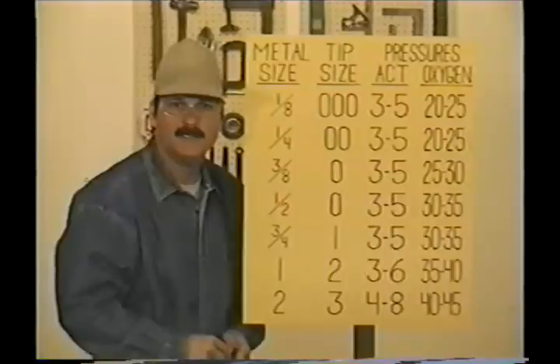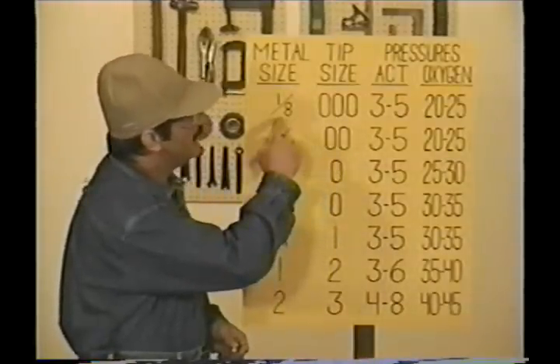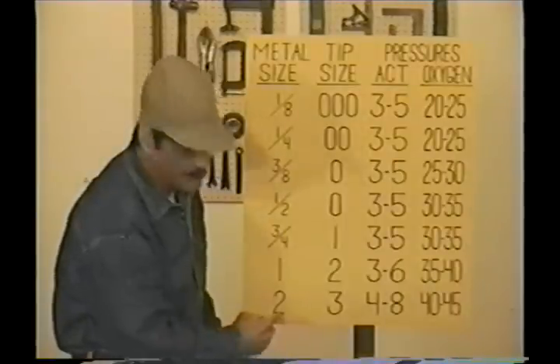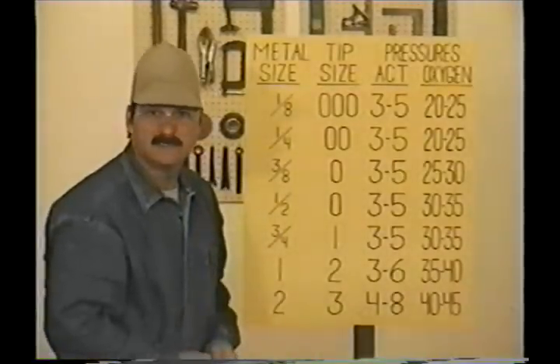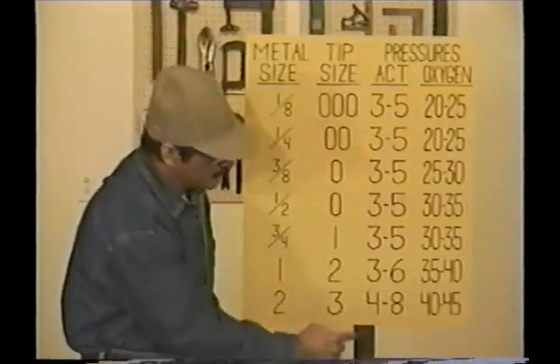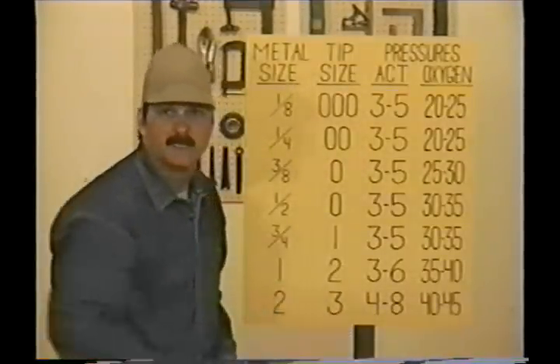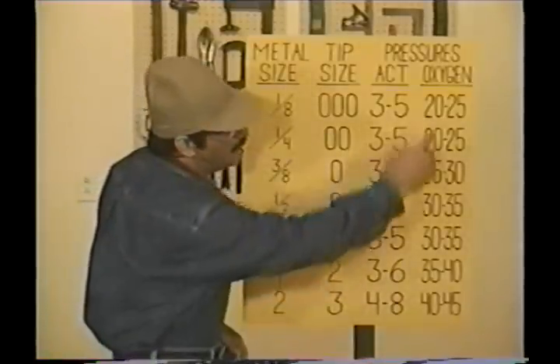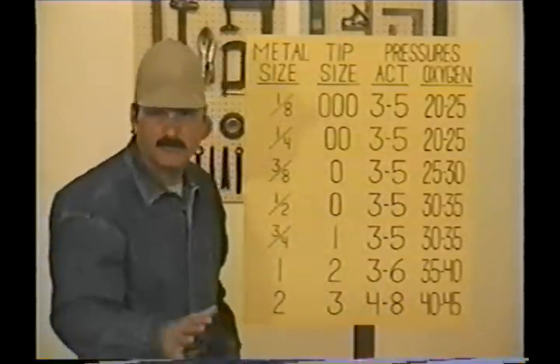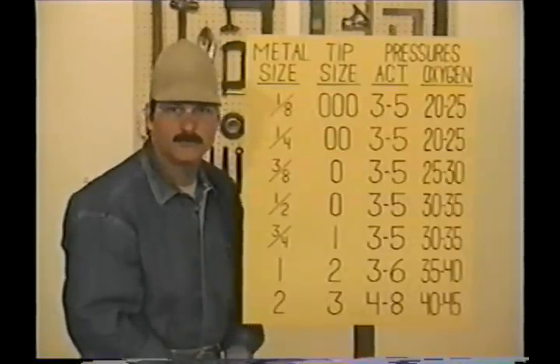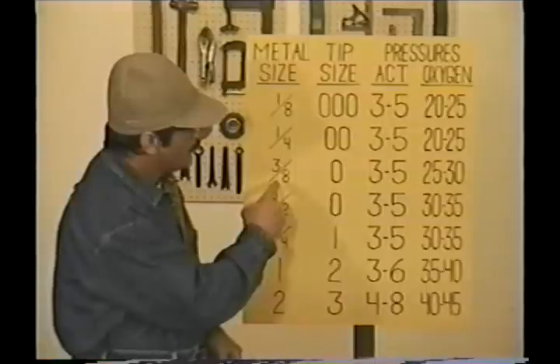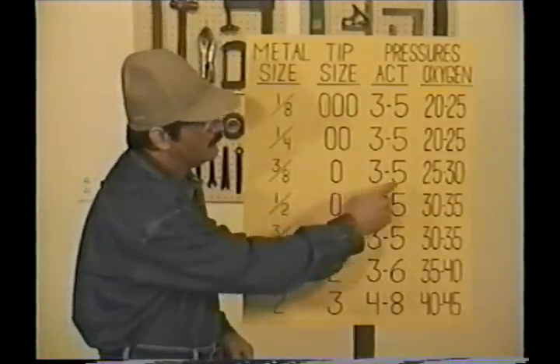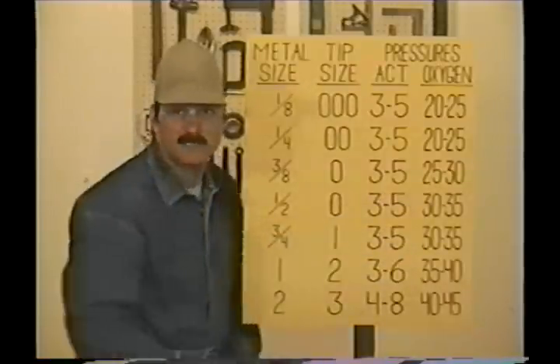Now, these tips come in different sizes, so let's take a look at a cutting chart. The commonly used cutting tips start at triple-aught for metals 1/8 of an inch thick, up to a number 3 for metals 2 inches thick. Notice that the same acetylene pressure, 3 to 5 pounds, is used on all the smaller tips, and even the large tip only uses 4 to 8 pounds. The oxygen pressure varies from 20 pounds to 45 pounds. The thicker the metal, the more pressure you need to get all the way through. We'll be demonstrating on some 3/8 flat bar using a single-aught tip with 5 pounds acetylene and 25 pounds oxygen.